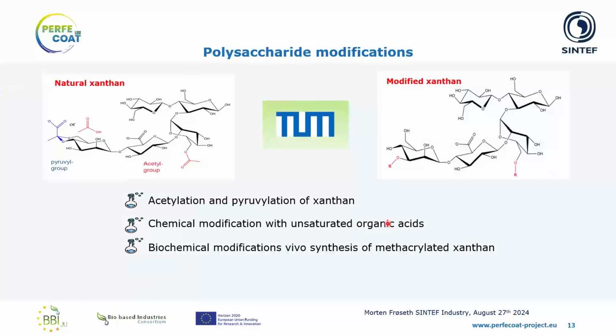We have also looked into another strategy when we talk about the xanthan gums. There we have actually modified, or I say we, that's the Technical University of München. They have modified the bacteria that produces the xanthan to change the final functionalities of the biopolymer. So they can tune the properties by introducing more acetyl groups in the final product, or even add acrylic functionalities into the system that can be used in UV curing of a final product.